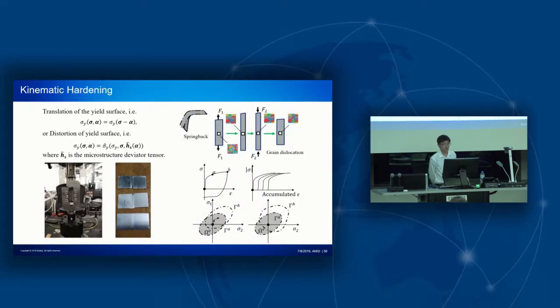Then, for the material kinematic hardening, we may need to introduce either translation or distortion of the yield surface. Material kinematic hardening is due to the redistribution of the grain dislocation caused by the cyclic loading. Or we can just perform some standard reverse shearing or tension compression test to gather some experiment data to calibrate the material kinematic hardening model.